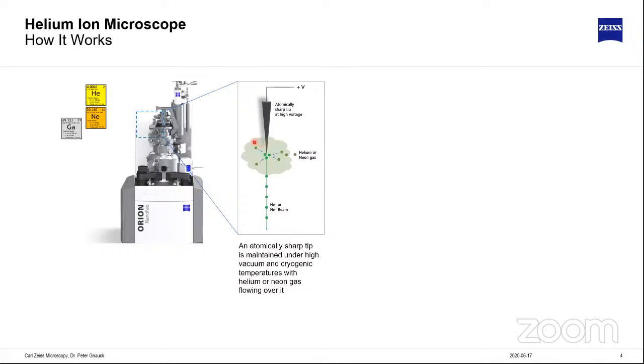For ions, we cannot produce field emission sources because we have a totally different ion generation process. What we're using here is a gas field ionization source, and that works in the following way. We have a very sharp tip, which is atomically sharp at the very end. We apply a voltage to that tip. That means we generate a strong electrostatic field in front of this tip. Then we bleed in our imaging gas, it's helium or neon. And the gas atoms are ionized in the strong electrostatic field in front of this tip, and they form an ion beam. And then the ion beam is just focused, scanned, rastered over the sample, and we're generating secondary electrons, and therefore we are generating a raster image very similar to what we do in a scanning electron microscope.